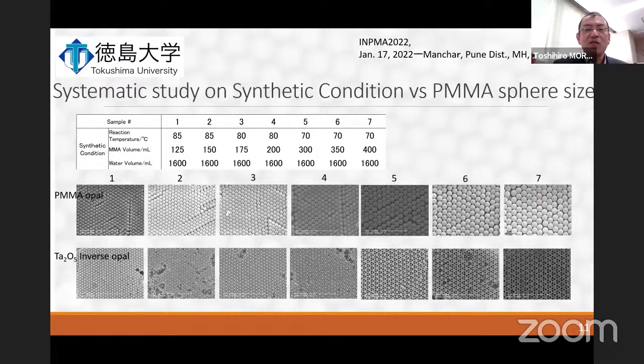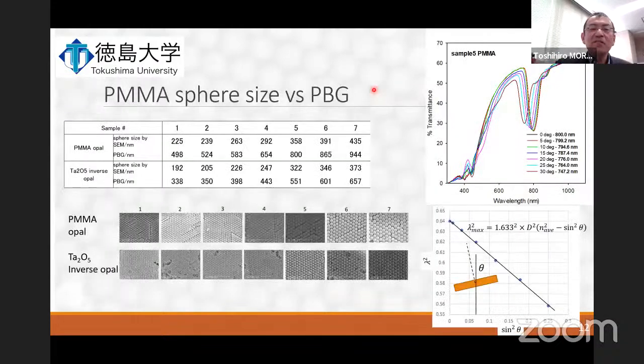The tantalum oxide inverse opals obtained after the careful heat treatment were also lined up neatly, possessing increased pore size in this order. You can see the regular pores in the seven samples. The first one is very small, but number 7 is very large. I'll show you the radius later. From the SEM images of the PMMA opal, this is the PMMA opal, and the tantalum oxide inverse opal here, we estimate the sphere and pore size of the opal and the inverse opals.